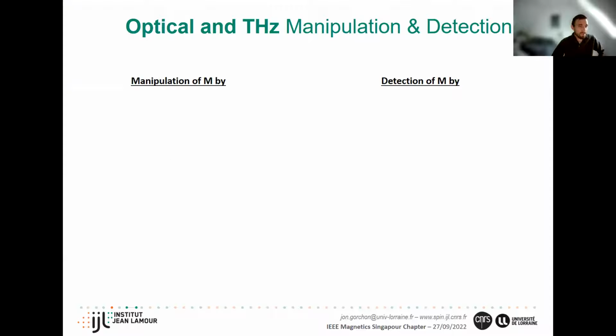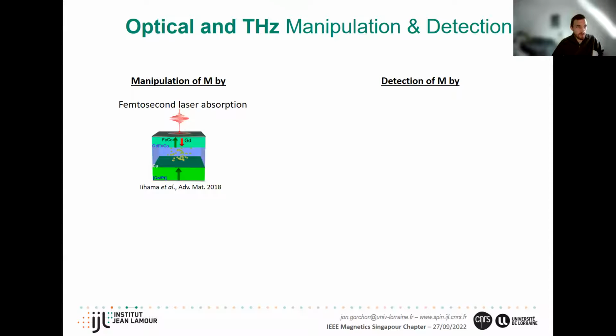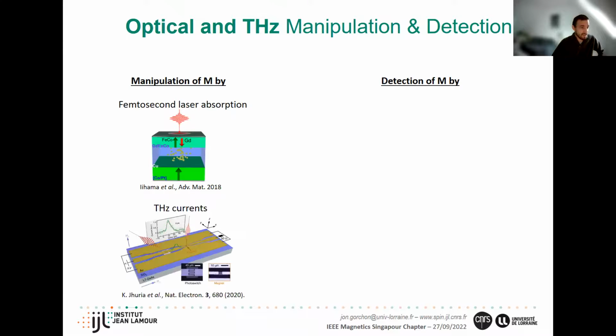What we're doing here in the lab is mostly manipulating the magnetization at ultra-fast timescales. One of the techniques that we use is to shoot a femtosecond laser beam onto a magnetic structure. We use a few different effects to generate spin currents and to induce dynamics. The second way that we use is to directly generate terahertz radiation. In this case, we use photoconductive switches.